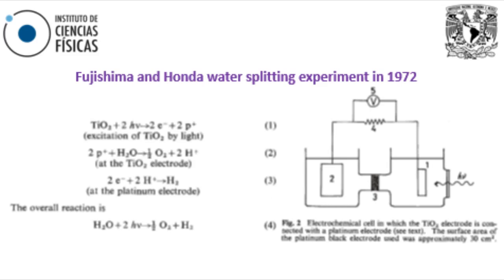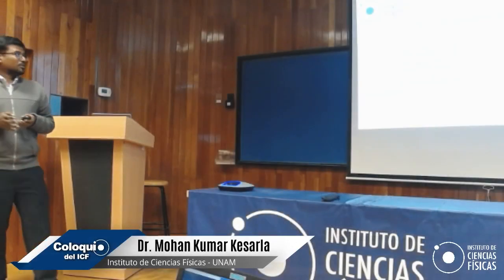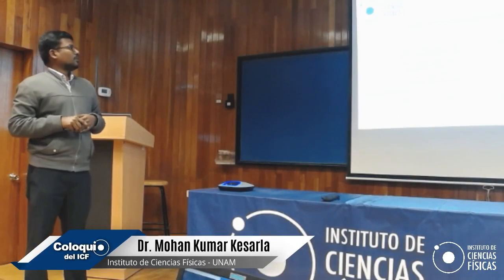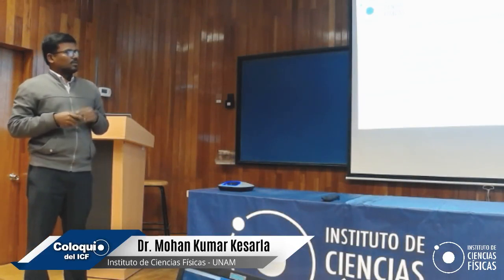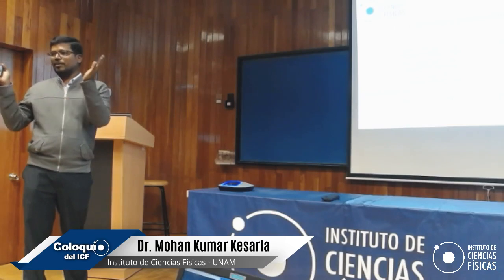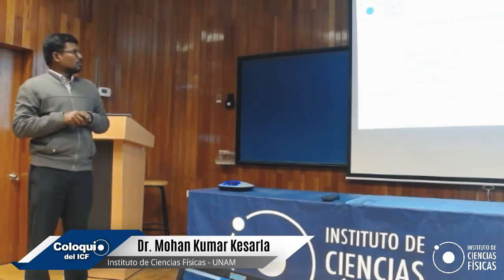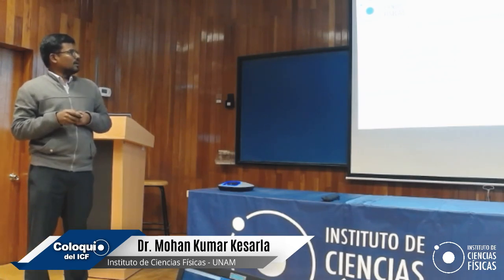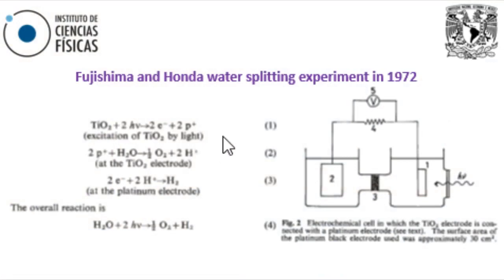They find some current flowing into this voltmeter, and then they find some oxygen is being liberated at the platinum. So then they got excited and tried to see what exactly is happening. After exciting with UV-visible light, the band gap of titanium oxide lies somewhere around 3.2 eV, so an electron-hole pair is formed. The holes formed oxidize the water to oxygen and two hydrogen ions, and the platinum collects the electrons and converts them back to hydrogen. So this is the first experiment which was conducted by Fujishima and Honda for the production of hydrogen.